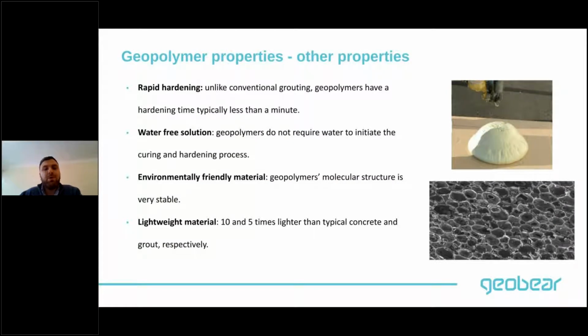Furthermore, there are other important geopolymer properties. For example, geopolymers can harden rapidly, so it only takes a few minutes or seconds for it to expand, harden, and cure. Geopolymers are also water-free solutions, so they do not require water to initiate the curing and hardening process. They are also environmentally friendly materials, so the molecular structure of geopolymers is quite stable. We've actually done some quite extensive testing on that from the environmental point of view to understand whether it's going to leach into water or contaminate aquifers or all that.